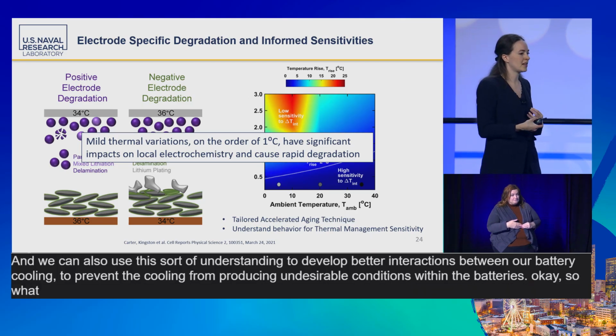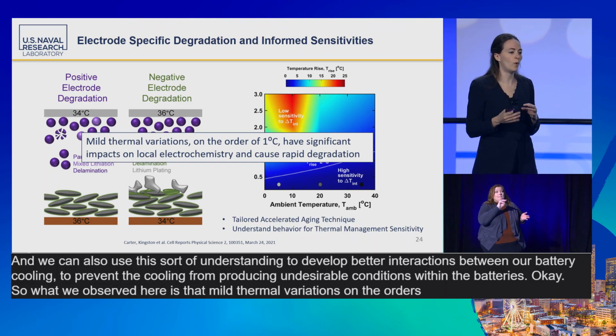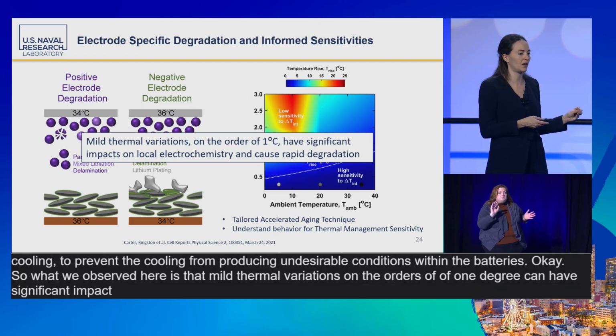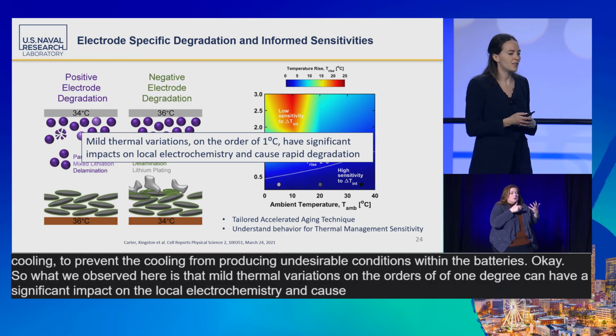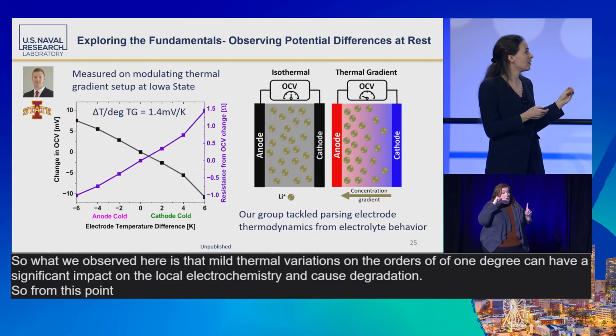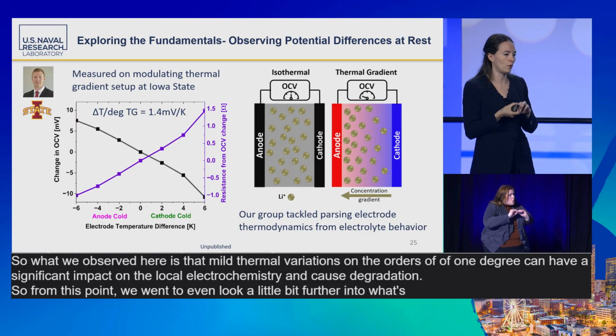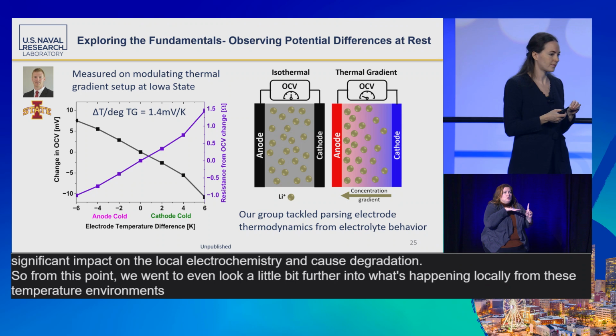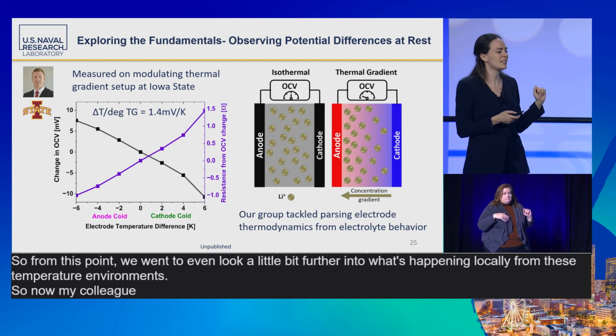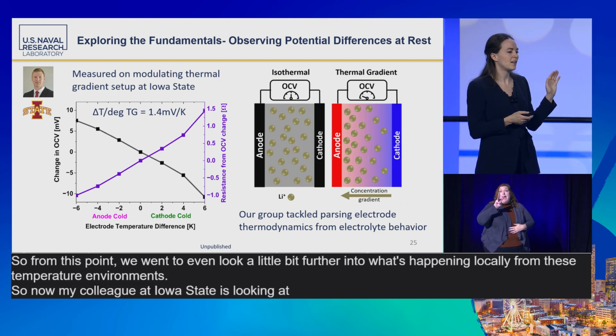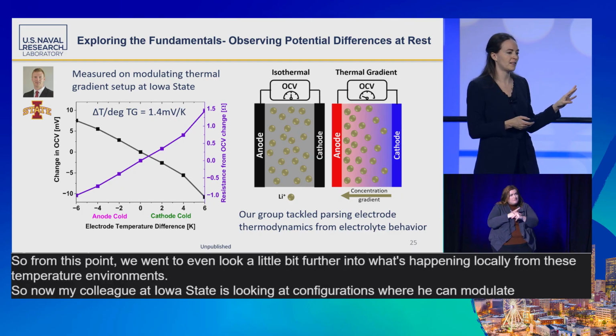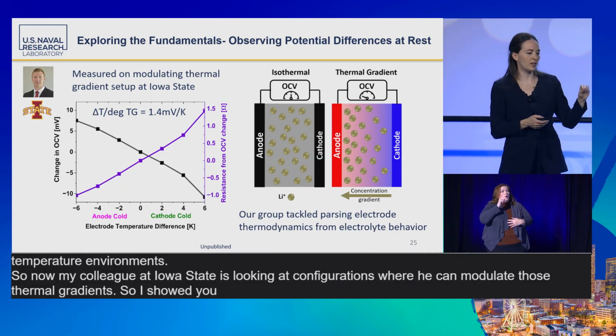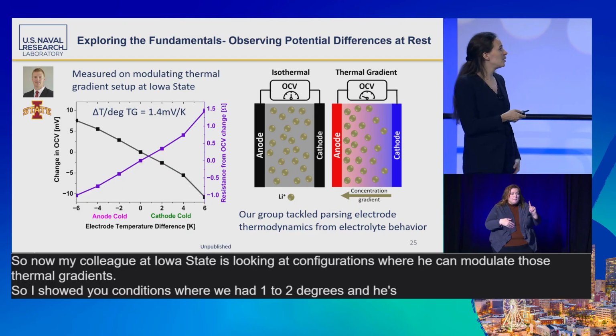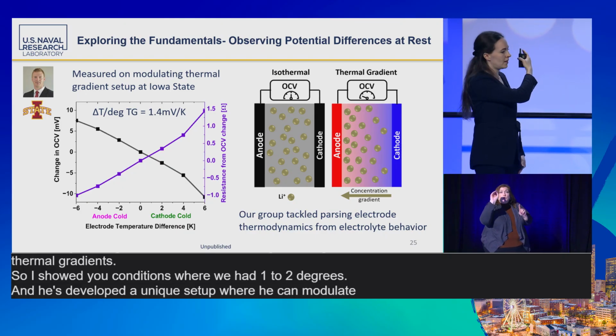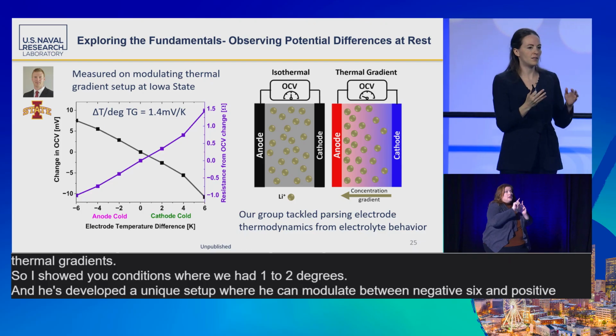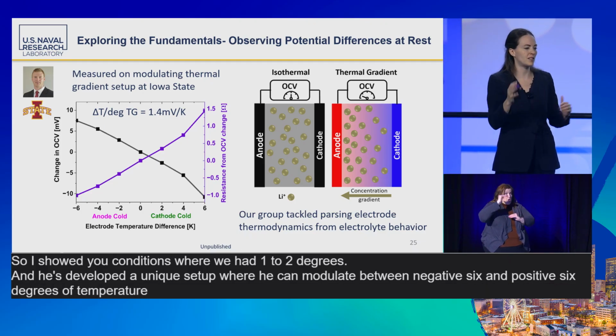Okay, so what we observed here is that mild thermal variations on the orders of 1 degree can have a significant impact on the local electrochemistry and cause degradation. So from this point, we went to even look a little bit further into what's happening locally from these temperature environments. So now my colleague at Iowa State is looking at configurations where he can modulate those thermal gradients. So I showed you conditions where we had 1 to 2 degrees, and he's developed a unique setup where he can modulate between -6 and +6 degrees of temperature variation from the positive to negative electrode.